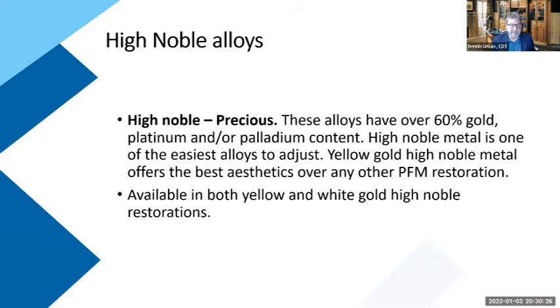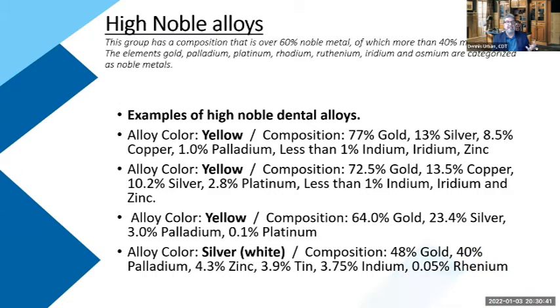So let's talk about high noble alloys. These precious alloys have over 60% noble metal content, and high noble metal is one of the easiest alloys to adjust, like I mentioned earlier. They're great for full cast crowns. Some of the high noble alloys on the market are the combinations you see on the bottom here: compositions of gold, silver, copper, palladium, indium, iridium, and zinc. There's a lot of different content in each specific alloy, and this group has a composition that's over 60% noble metal, of which more than 40% must be gold in order to qualify as a high noble alloy.